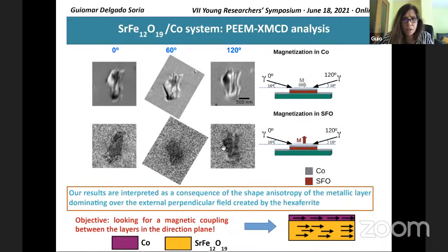But for example, in the strontium ferrite platelet, we see the iron L-edge. In the images at all the angles, we always have a black domain that corresponds to an out-of-plane magnetic domain. So there is no correlation between the magnetic domains of both layers. Our results are interpreted as the shape anisotropy of the cobalt layer dominating over the strontium ferrite out-of-plane magnetization.